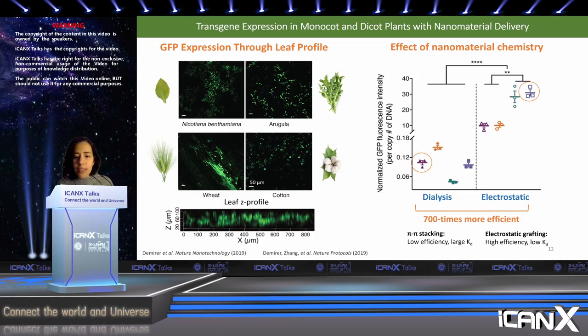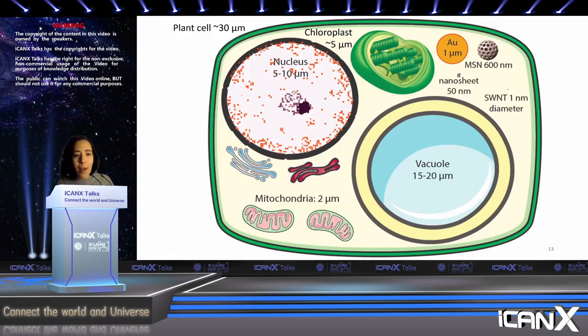And indeed, I'm not showing this data, but some of our recent explorations of these constructs suggest that the DNA does not even have to desorb from the carbon nanotube for it to be transcribed into a functional protein. And to give you a sense of the relative size scales that we're talking about, I've depicted here roughly to scale a plant cell, where by far the largest organelle is a large central vacuole, and some examples of previous particles that have been used for biolistic delivery. Compared to the inner diameter of a carbon nanotube, these are much larger particles. And so hopefully the schematic can help you appreciate some of the mechanisms by which these single wall carbon nanotubes are able to independently enter plant cells.